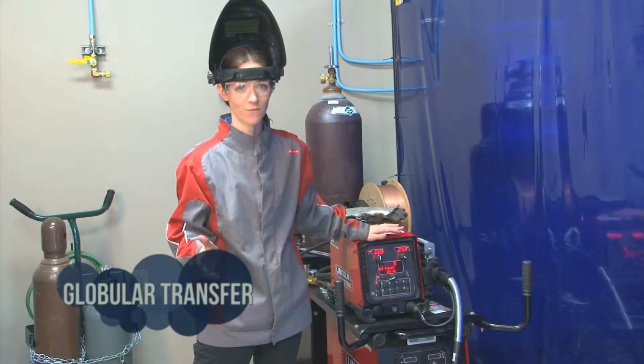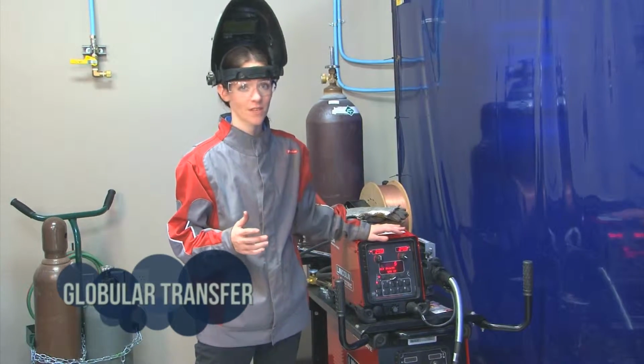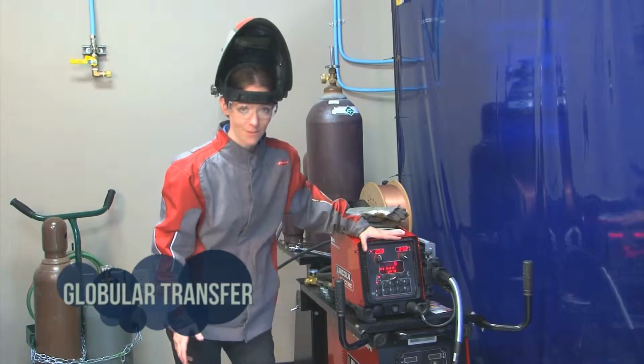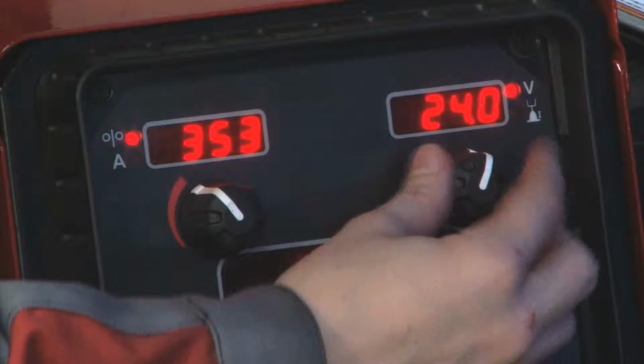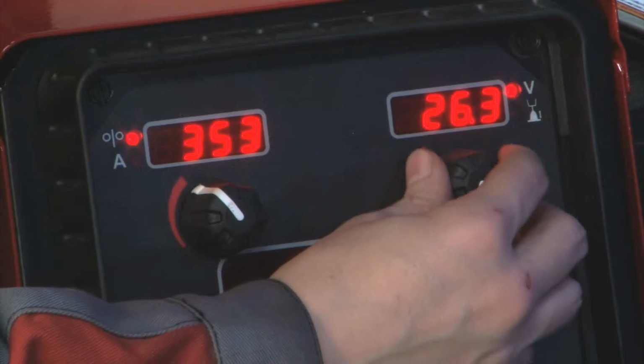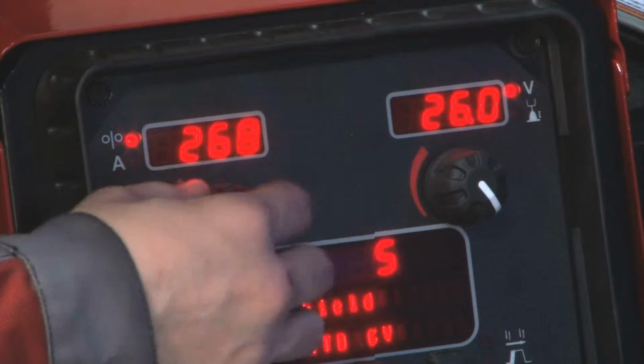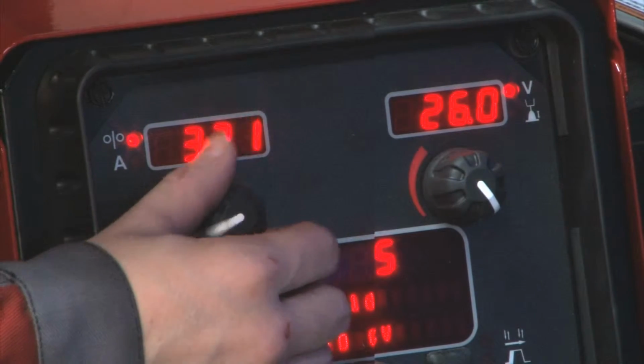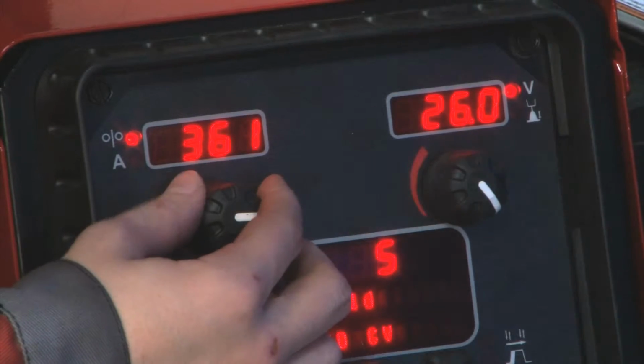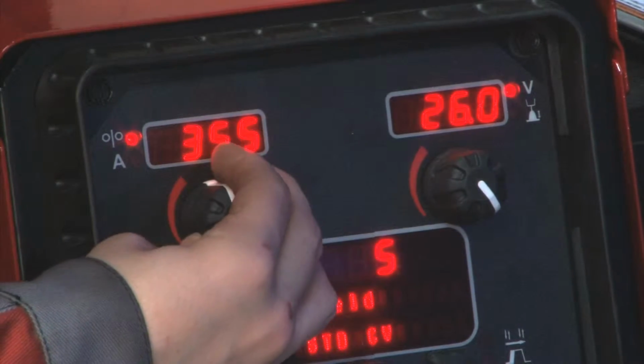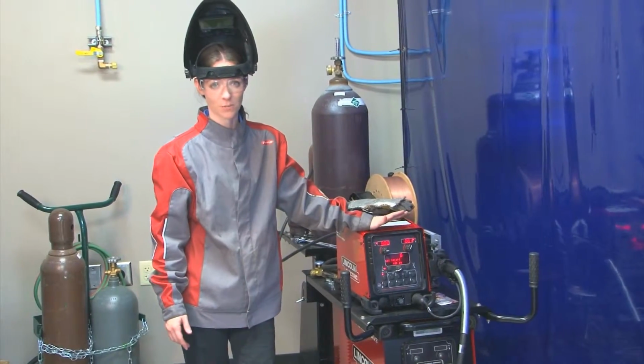Settings for globular transfer usually range between 24 and 25 volts. So what we have is globular settings. When we want to go to spray, we need to increase our voltage to about 26. And we're going to increase our wire feed speed to just over 350. This should give us a fairly good spray transfer.